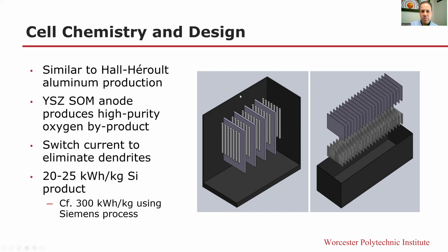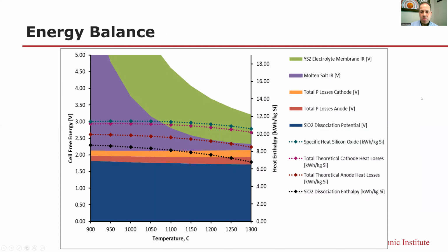So this is what the cell looks like. This is a schematic over here in the center with the silicon cathodes and zirconia anodes in between them. And then a full-size cell would have a very large number of cathodes and a large number of anodes as well. The predicted energy consumption is about 20 to 25 kilowatt hours per kilogram, which is less than 1/10 of the 300 kilowatt hours per kilogram using the Siemens process for solar and electronics grade silicon. Looking at the energy balance, there are two energy stacks here. One of them is the resistance of the cell that leads to a potential.